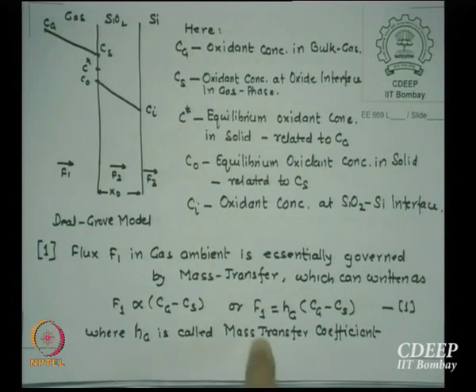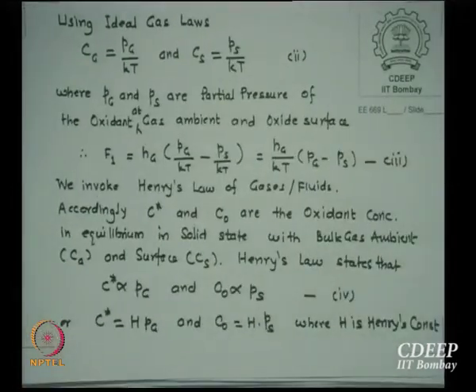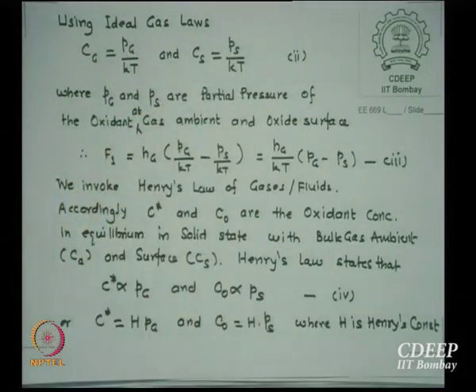So the first thing I do is write hg into Cg minus Cs as the first flux, where, I repeat, hg is called the mass transfer coefficient. We define Cg by the ideal gas law, PV is equal to RT. There is nothing great about it. This is concentration, so Cg is equal to Pg by kT, with n equal to 1 molecule, so RT is kT. So Cg is Pg by kT, Cs is Ps by kT, where Pg and Ps are the partial pressures of the oxidant in the gas ambient and at the oxide surface. Again, Pg is in the gas stream, and Ps is near the interface of oxide and gas stream.